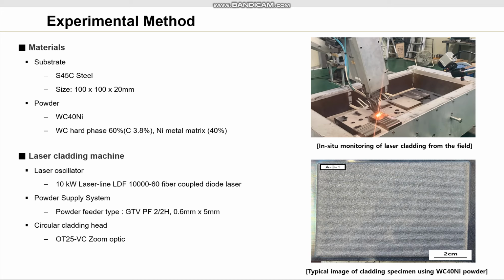And then we used tungsten carbide and nickel-based alloy powder manufactured by Metco. This powder mainly consists of 60% tungsten carbide and 40% nickel. The nickel metal has lower mechanical properties than cobalt, but has excellent corrosion resistance and oxidation resistance. The laser cladding machine consists of a 10 kilowatt laser oscillator manufactured by Laserline and a powder feeding system manufactured by GTV. This machine is being operated by a corporation in South Korea.